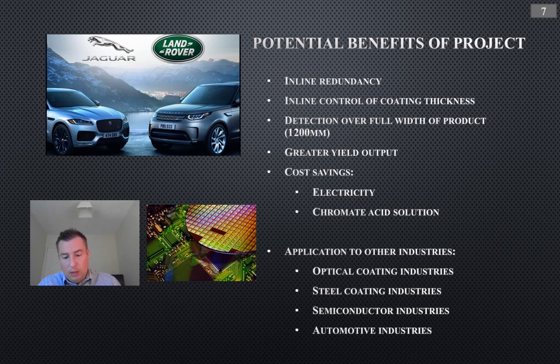And what's good about this research is it can also apply to other industries where you need to measure nanometer scale coatings, which could be the optical coating industries, steel coatings where you use another coating such as zinc, semiconductor industries, so it could be silicon dioxide on a silicon substrate, or it could also be automotive industries when you want to measure the thickness of paint.